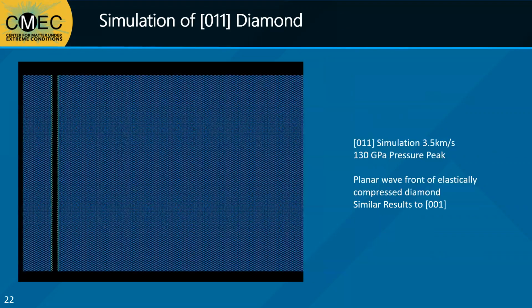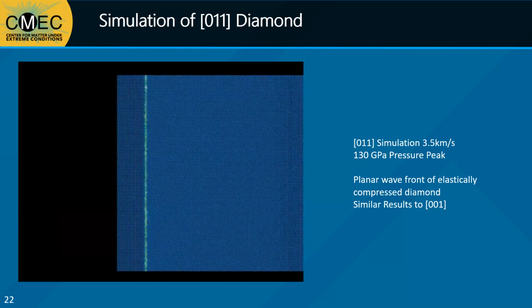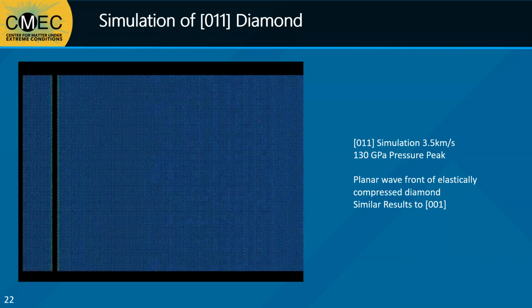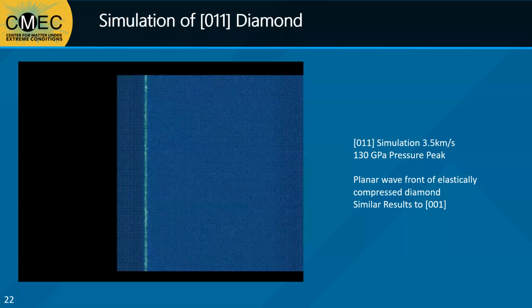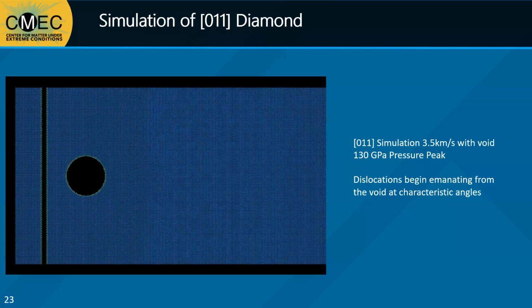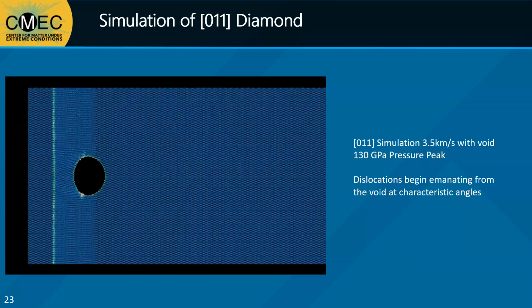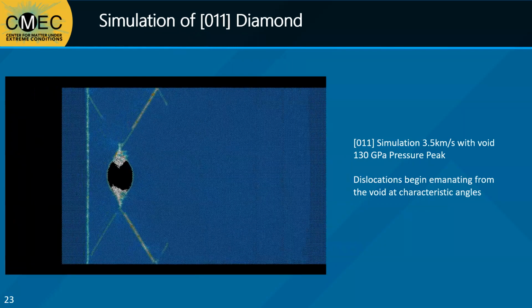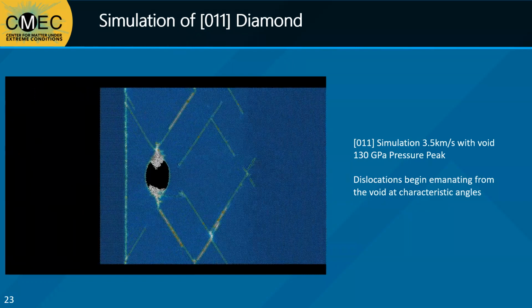We also performed our simulations along the 011 direction. In the case without a void at 3.5 kilometers per second, we see even less activity compared to the 001 orientation. No defects form, simply elastic compression. However, when we introduce a void in the 011 case, we finally see some defects emerge. Here we can see symmetric defects emanating from the void at characteristic angles, which seem to be leaving behind stacking faults.